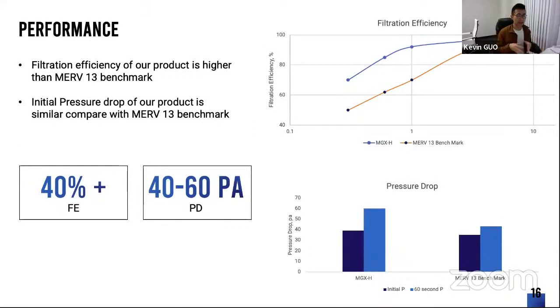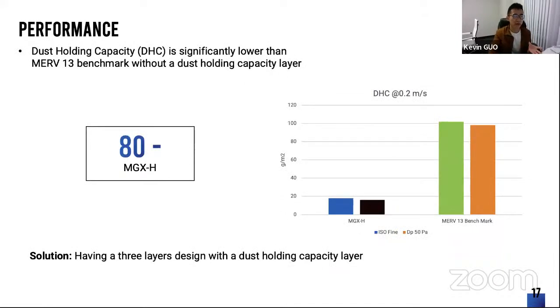We also collected some data based on our own developed filter media and benchmarked with regular MERV 13 filters. If you look at those graphs, you can see nanofiber filter media shows over 40% higher filtration efficiency with a similar pressure drop compared with a regular MERV 13 filter. However, the nanofiber filter media without a dust holding capacity layer does show inferior dust holding capacity performance, which is not ideal for HVAC filters. But this problem can be easily addressed by adding another dust holding capacity layer on top of the nanofiber. For example, we can add another melt blown layer.